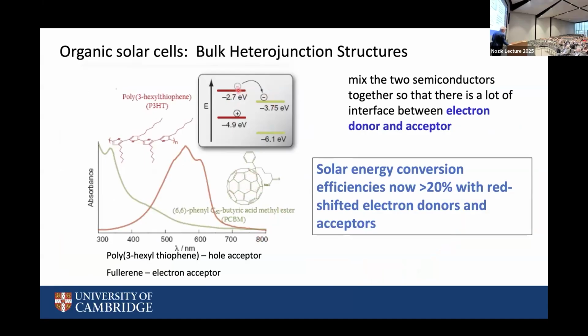And what we see is, in this case, the electron, the excited electron, following absorption of the photon on the polymer, drops to a lower energy as it moves to fullerene. That's how we drive the charge separation. Over many years, the material sets have changed. There's been wonderful work, very significantly in China these days, and there are several reports, pretty reliable reports, of a 20% power conversion efficiency for this sort of organic solar cell.